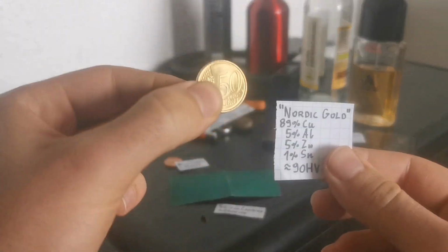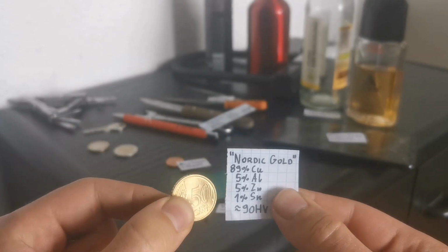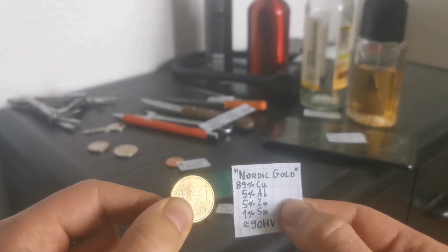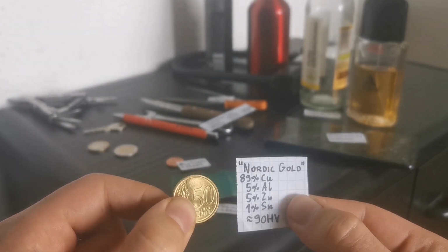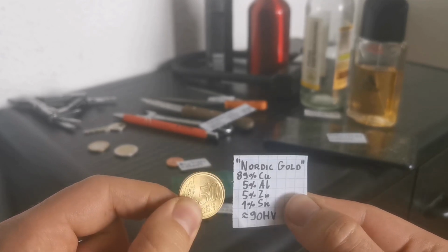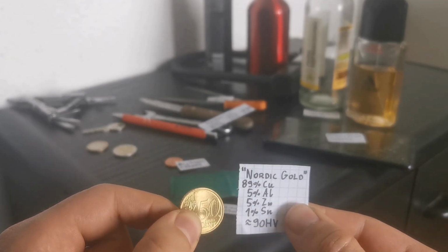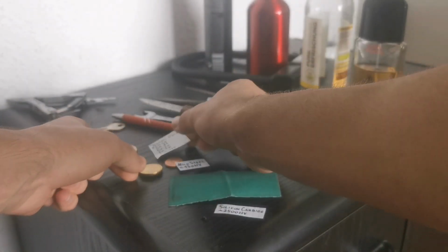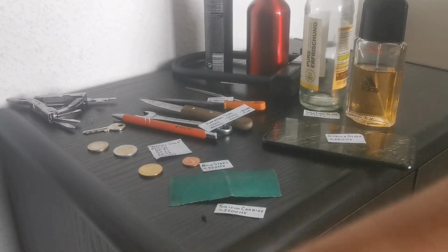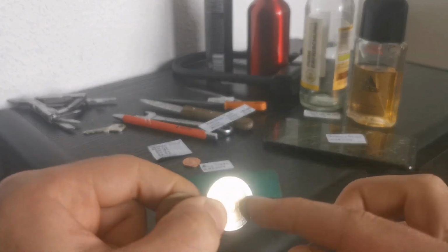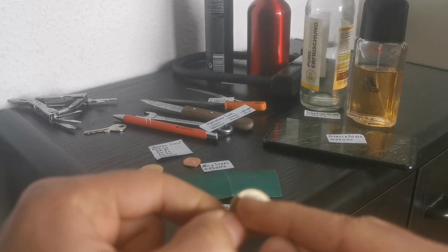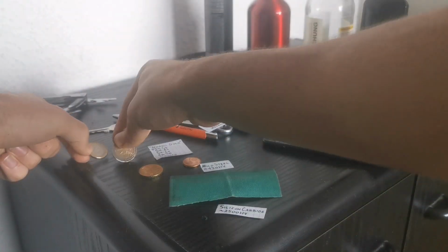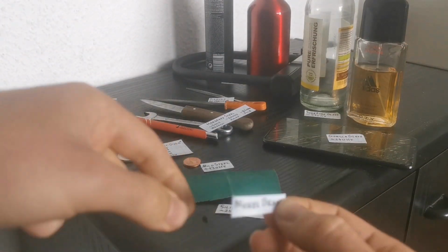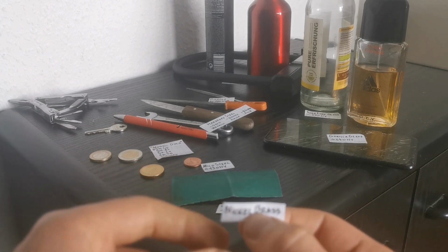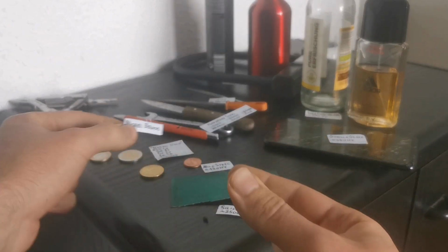The euro cent is the alloy named Nordic Gold, with mainly copper and additions of aluminum, zinc and tin, for an overall hardness of around 90 HV. And on the euros, the silvery part is made out of cupronickel, a copper-nickel alloy.